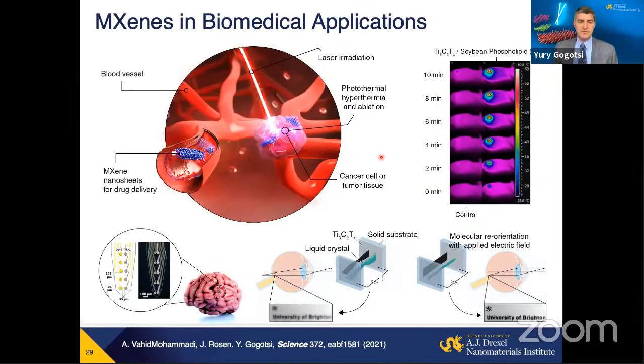Along with the optical applications, biomedical applications of MXenes are among the fastest growing at the moment and expanding here. Much of it started with using MXenes for photothermal therapy. And again, recall pictures that I showed to you of MXenes having plasmon resonance at different wavelengths, and a number of them have it in the near infrared or infrared range. For example, titanium carbide Ti3C2 close to 800 nanometers, niobium carbide Nb2C goes further into infrared. And they appear to be very efficient light to heat converting materials.